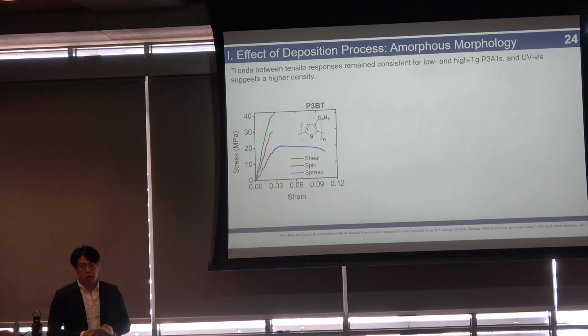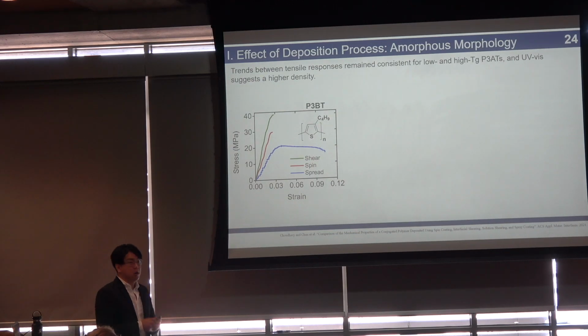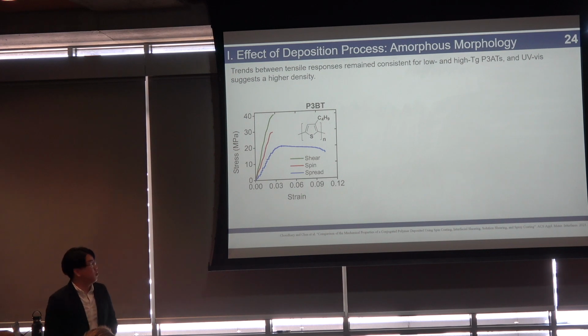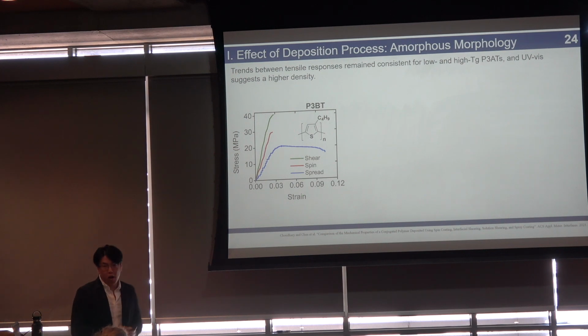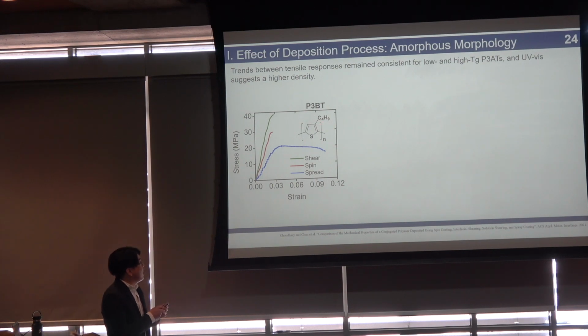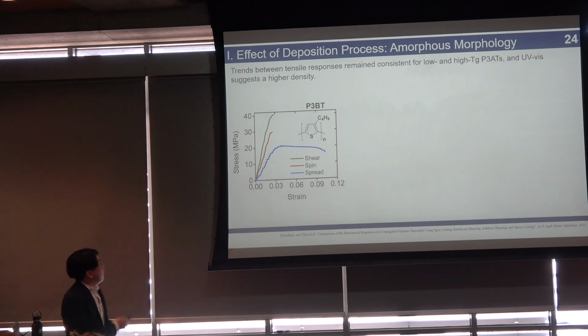P3HT, which we used earlier, is a low glass transition temperature polymer. What we did to start to investigate the morphology is use a proxy polymer by shortening the alkyl chain length. And by shortening the alkyl chain length, your glass transition temperature goes up. And for the mechanical responses, we actually see the exact same behaviors. Spread films are very, very stretchable, and sheared films are stronger than spin-coated films.